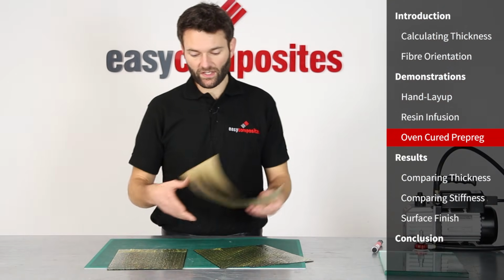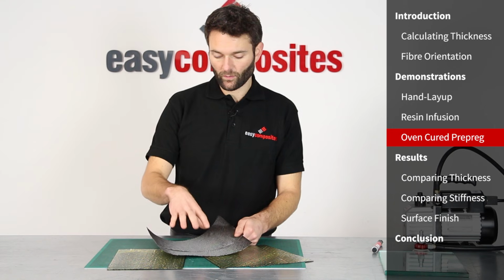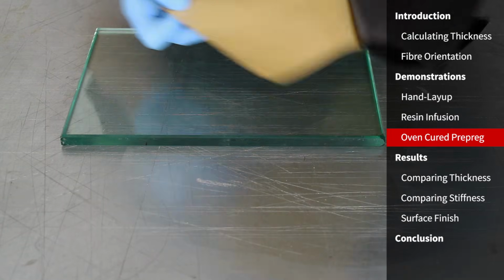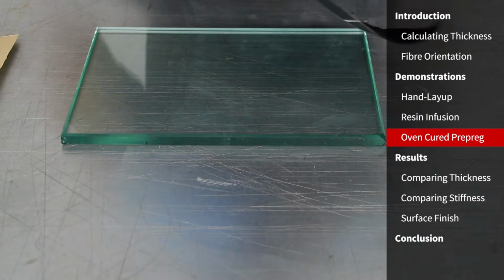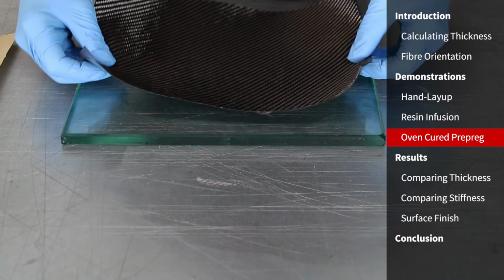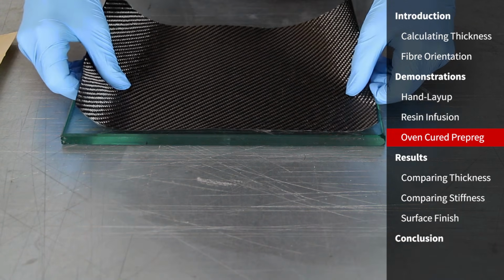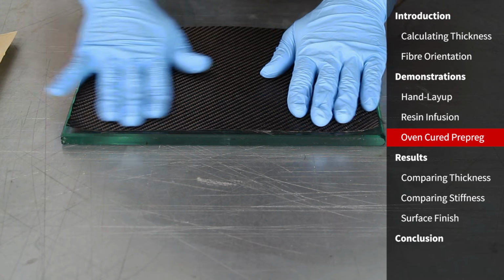And then we'll finish our laminate top and bottom with a layer of the 240 gram Easy Preg. So this is the out-of-autoclave surfacing prepreg that's going to be necessary, certainly on the A side of the sheet, to give us that pinhole free surface finish.